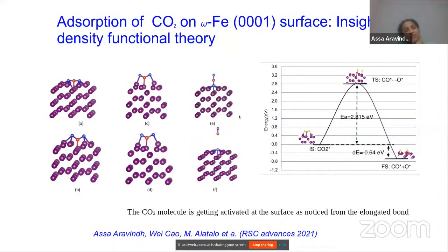So DFT can also be used to study, as I was saying, a wide range of properties. This is one example in which we tried carbon dioxide attachment on the surface, again the omega Fe surface, which I mentioned in the initial slide. During steel production, a lot of carbon dioxide is produced and the steel samples are exposed. So there is a possibility that carbon can attach, and carbon dioxide can come in contact with the surface. So we used these omega Fe surfaces to see whether they can capture carbon dioxide and whether it undergoes any spontaneous splitting.